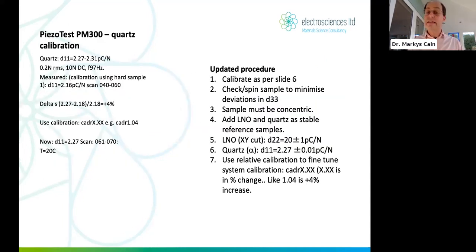Quartz is a standard that's used across the world in any piezoelectric measurements, whether it be direct or indirect, whether you measure the displacement with applied voltage using interferometry, or a dielectric resonance method, or using a Berlincourt type method like we're describing here. And you might ask yourself, how do I calibrate the response of my system, the PM300 system, using quartz, where the d33 is only 2.27. It's very, very low d33.